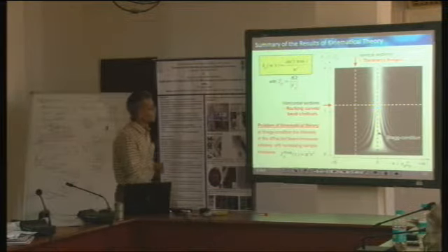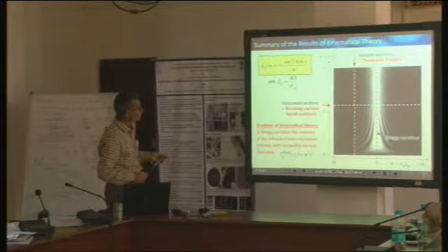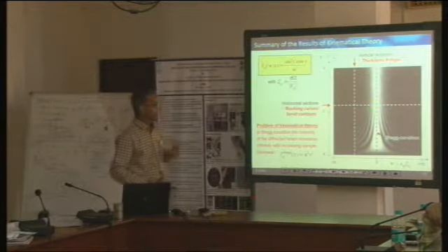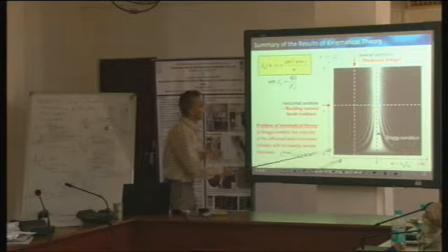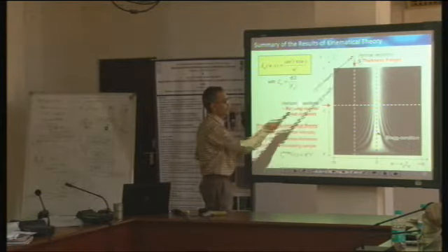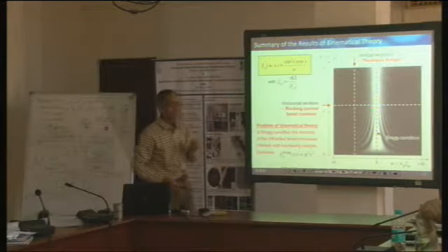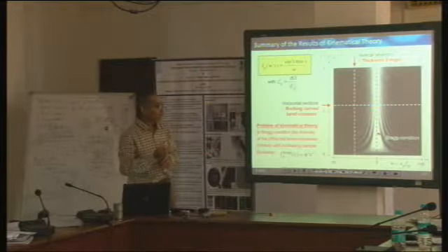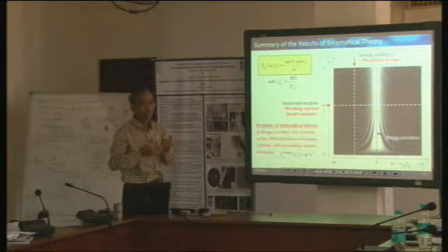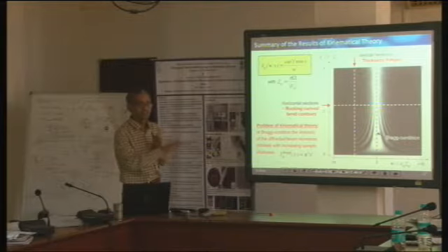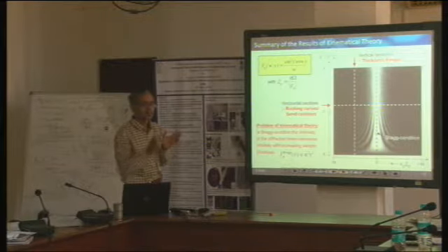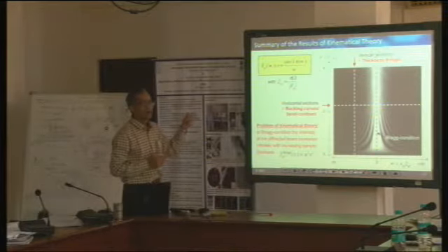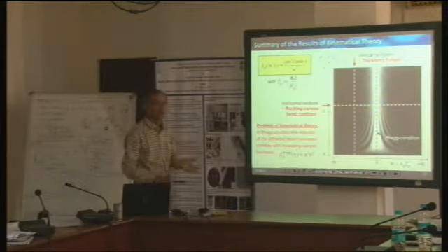What is another problem? Let's try to look for another problem. Okay, so we are considering the case along this dark line. That dark line corresponds to a situation wherein my sample satisfies the Bragg diffraction condition exactly, and we are looking at the influence of increasing the thickness under such conditions, that is exact Bragg diffraction condition, and this is going to expose the problem with the kinematical theory.